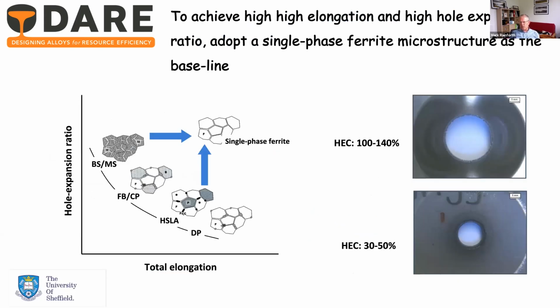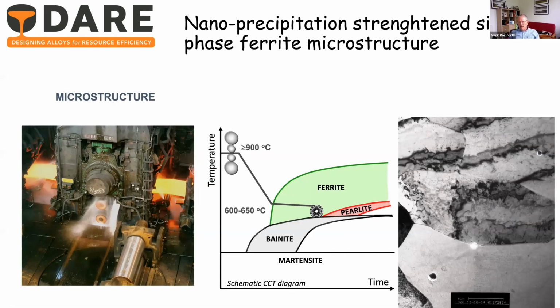So the strategy here was to go for a single phase ferrite, in other words, the structure that would give the maximum ductility. So this is another version of the banana diagram, where we're plotting hole expansion ratio against the tensile elongation. And most materials, again, sit in a banana shape, whether the dual phase steels, HSLA steels, and so on. So the approach was to go to a ferritic baseline and use the strategies of a fine grain size and a high loading of precipitation to achieve the strengths of up to 1 gigapascal that we were seeking.